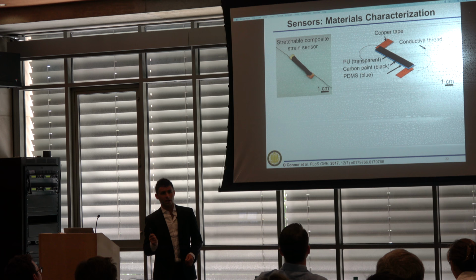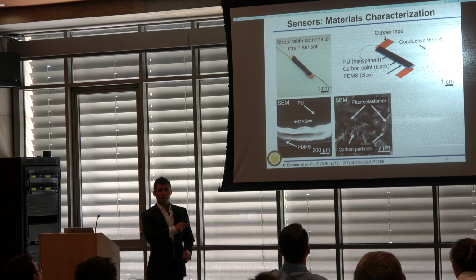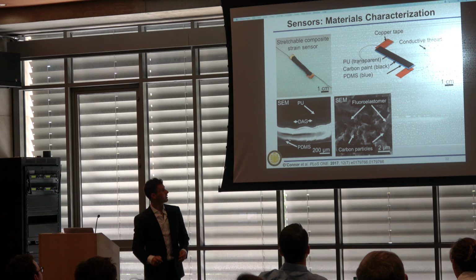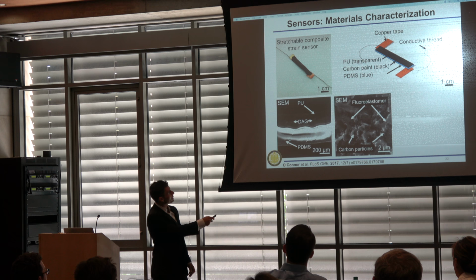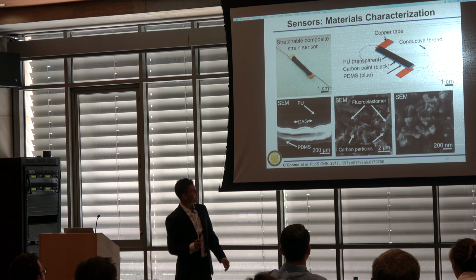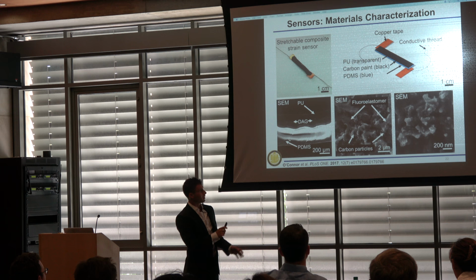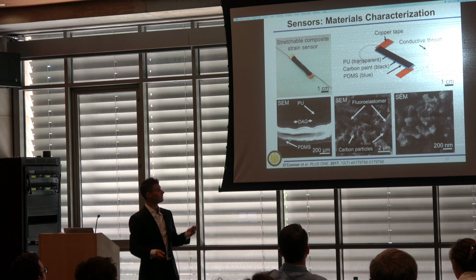And here are some SEM images of the cross section. We have about 300 microns of PDMS, 50 microns of DAG, and it's encapsulated in polyurethane. If we look at the microstructure, we can see how it's formed. We have a fluoroelastomer matrix, and embedded within it are these nano-sized carbon particles. Zooming in closer, you can see the graphite particles and carbon black particles are on the order of sub 100 nanometers. As they stretch, the interparticle distance will increase, and the resistivity and resistance will go up across the sensor.